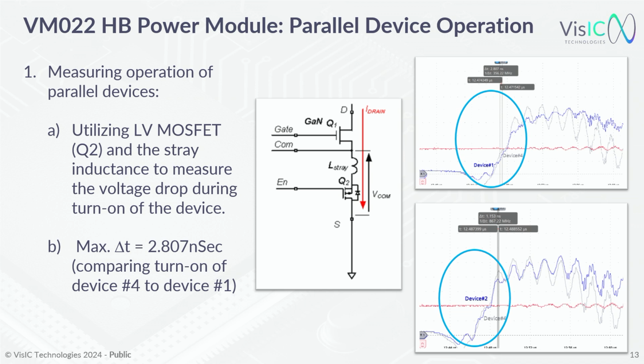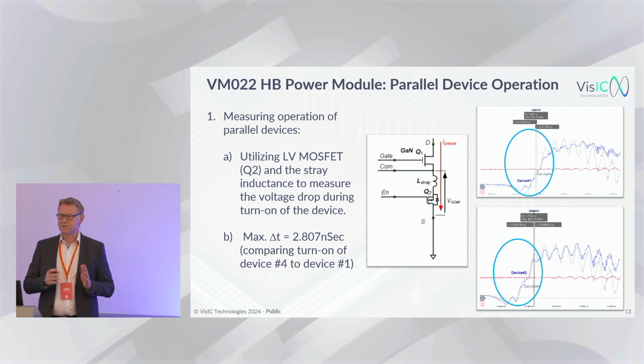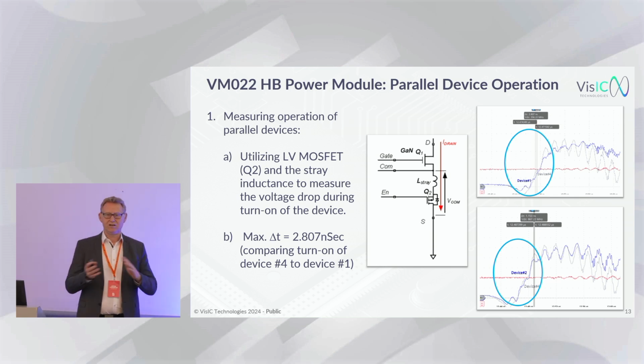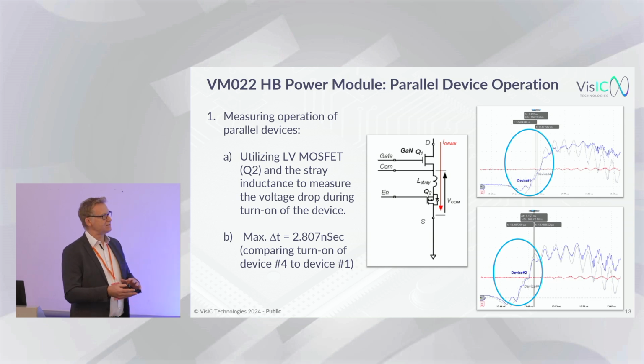One important point was paralleling of the devices. Now you're using four pre-packed devices, but they all have different properties, and we are not binning our devices. As I showed you before, we already have a very narrow range of RDS(on) spread due to processing, but the threshold voltage spread is also very narrow. Then we measured how much deviation we really have in turn-on and turn-off between the different devices. This is roughly 2.8 nanoseconds of delta T between the worst performing and best performing part. This means at the end of the day, all the switches are switching on at the same time. So you need a low inductance packaging on the one side, you need capacitors, and then you can control even four devices in parallel with this kind of approach.